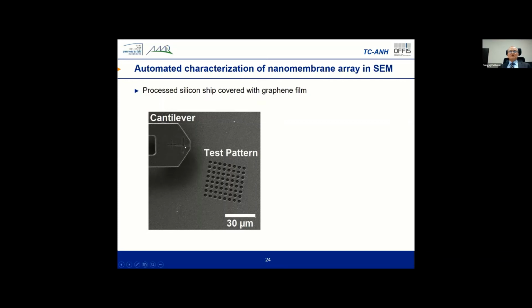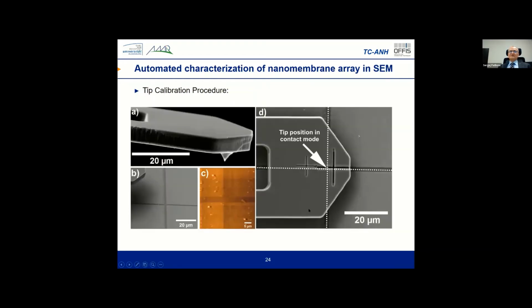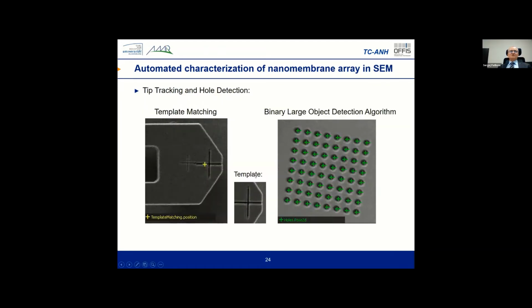Obviously, you have imaging here from the top of the scanning electron microscope. So you have to track a special pattern, this cross pattern here on the back side of the AFM cantilever, and on the downside of this cantilever you have the tip, obviously. This tip is exactly the tool for nano indentation here. So you have to take this tip to every single one of these nanomembranes, do indentation, and record the results. This is how we prepare the automation, tip calibration, obviously. So this FIB milled cross pattern, and this is the position of the tip on the other side of the cantilever, right? For tracking, we use template matching for the cross pattern on the cantilever, and a blob algorithm for detection of the position of the nanomembrane here.